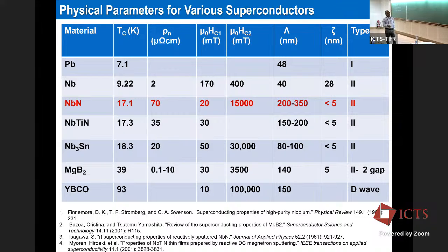On the other hand, the coherence length is small, and this allows us to have a superconducting phase, meaning a transition temperature of around 14 Kelvin, in a thin film of around 5 nanometers. So these are some of the advantages. And later on, we can think of, as you were saying, temperatures of around or less than 40 K. So MgB2 looks to be a better candidate there. Once we optimize things here, we can look for an opportunity to work with MgB2 kind of materials.